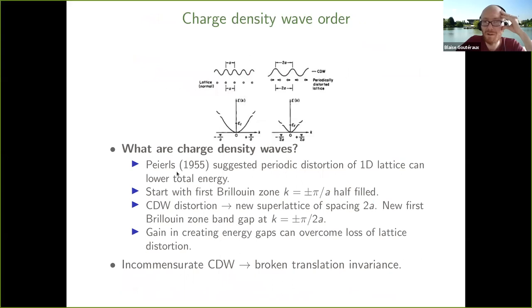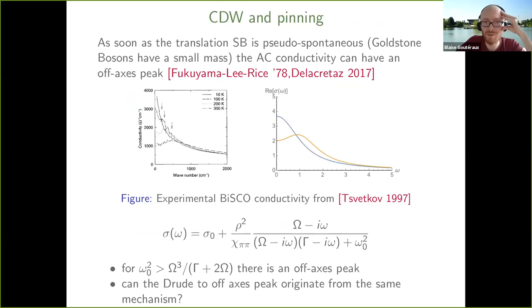So if I may interject, at low temperatures it's true, but at high temperatures there are some. You're right. So at this point, when you go to very high temperatures, you start to violate Fermi liquid behavior and you get this sort of fluctuating response. I agree with that. I'm basically talking about low temperatures. From 400 Kelvin in this metal down to 40 Kelvin, at optimal doping when Tc is at 40 Kelvin, that regime is all pure Drude. At high temperatures, it's deviating, right? And there you guys have a point, I agree.